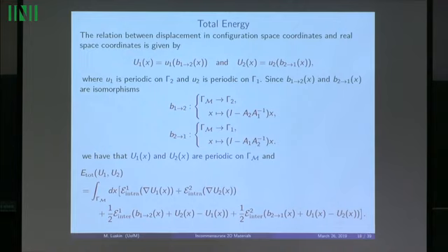So now I can define a cap U1 and a cap U2. Those are the real space disregistry. So I'm going to solve this problem in real space. Now we put all this together and we have an elliptic PDE on the Moire cell gamma M.